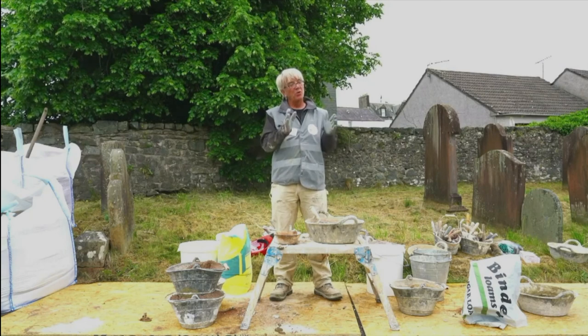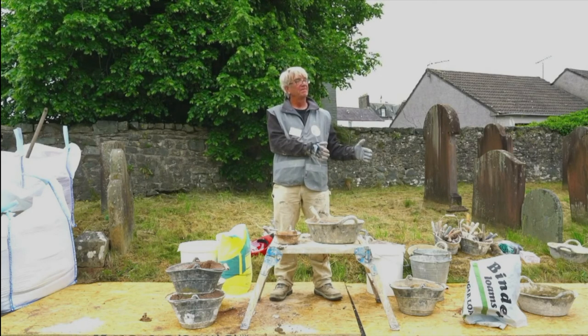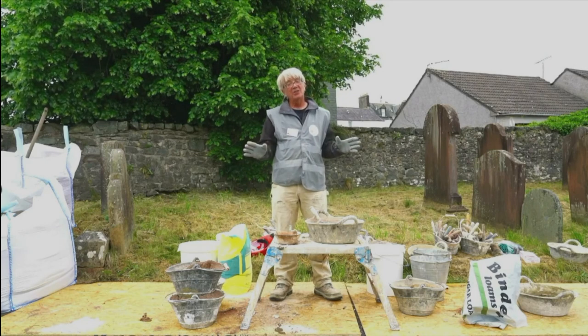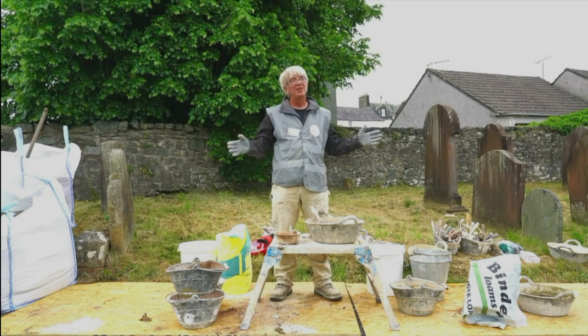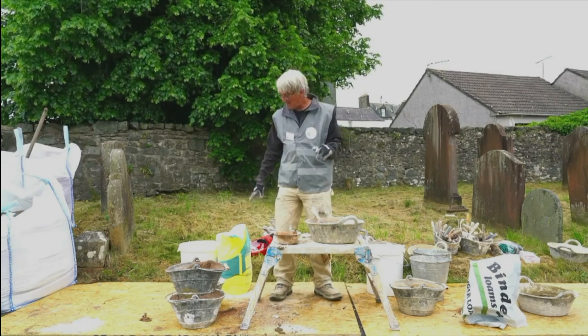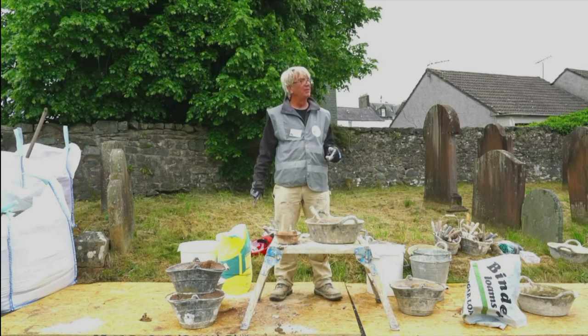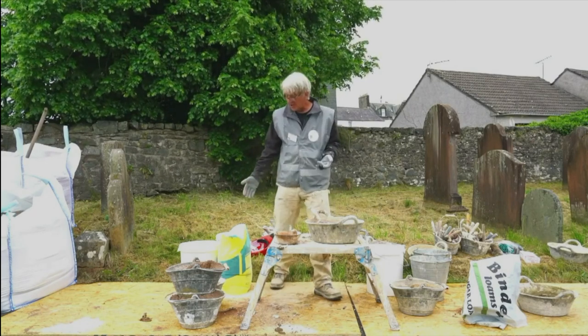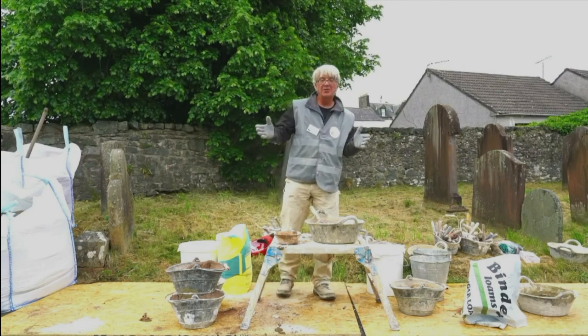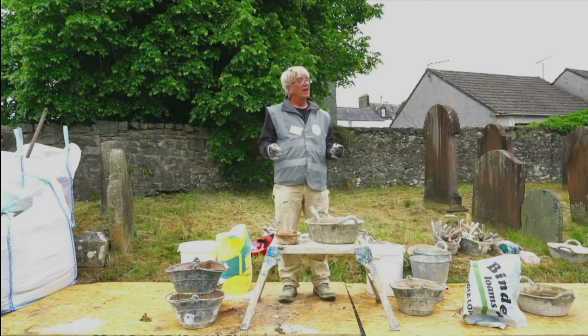And I would say that 1 to 3 with lump lime is designed to deliver a mortar that is 1 to 2 in binder. Typically, clearly we're using powder which is 100% binder. So although I generally myself still mix it 1 to 3 because I'm as conservative as everyone else, this is what we've had all our success with over the last 15 years, mainly success. I'm reluctant to change, but you could very reasonably mix it 1 to 4 with powder, because you're going to get 1 to 2. In my kitchen sink experiments, this quicklime expands 2.2 times on slaking. So actually, yeah, if you mix it 1 to 4, you'll get less initial shrinkage. It will still be as good as it needs to be in terms of binder proportion and so on. And there is a saving there.